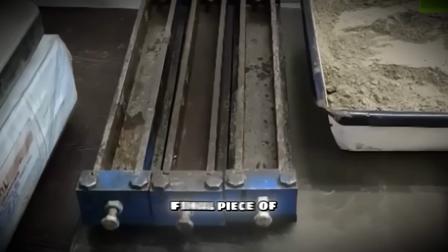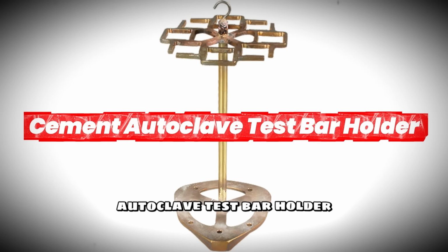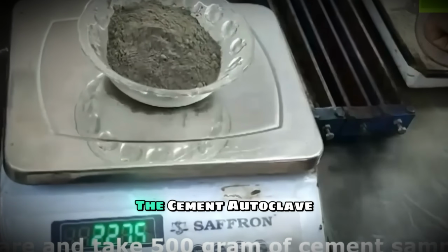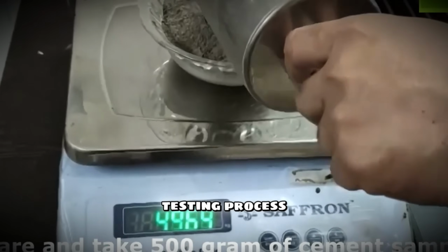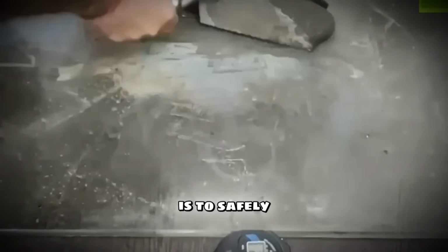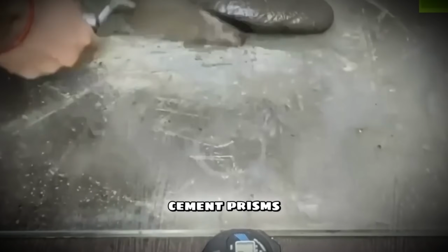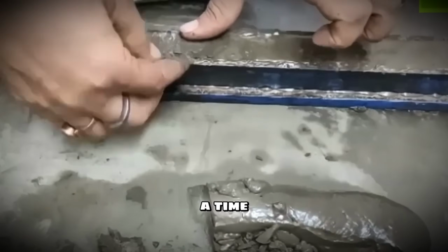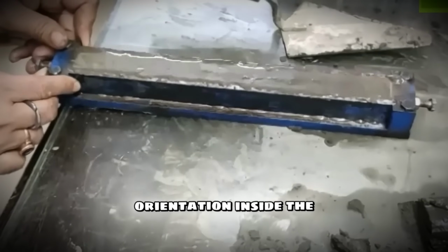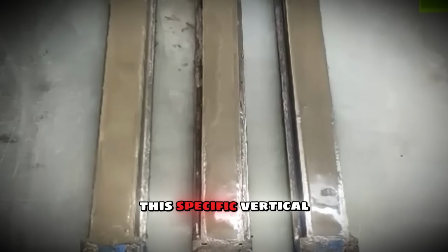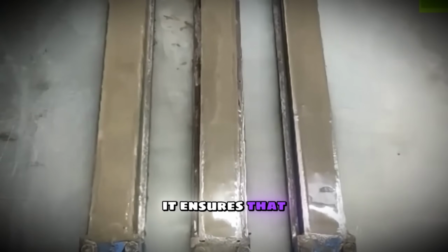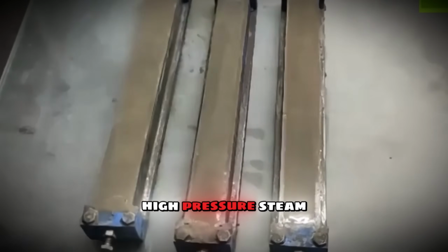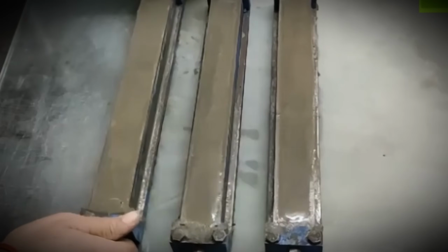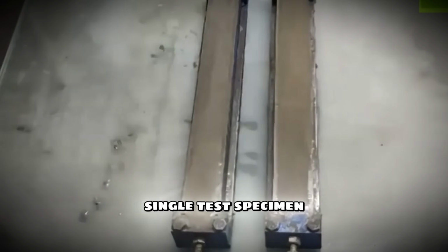That's why the final piece of our testing puzzle is the cement autoclave test bar holder. The cement autoclave test bar holder is an unsung hero of the testing process. Its primary usage is to safely and securely hold the molded cement prisms, usually up to 8 bars at a time, in a vertical orientation inside the autoclave chamber. This specific vertical positioning is crucial. It ensures that the saturated high-pressure steam circulates freely and evenly around all 4 sides of every single test specimen.